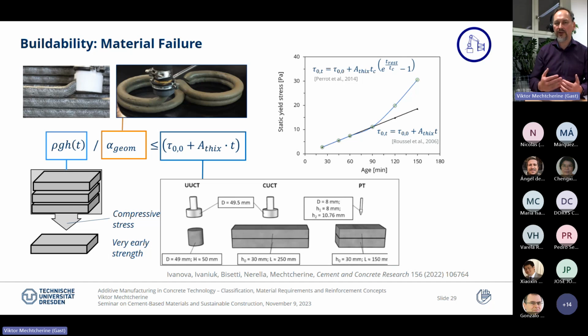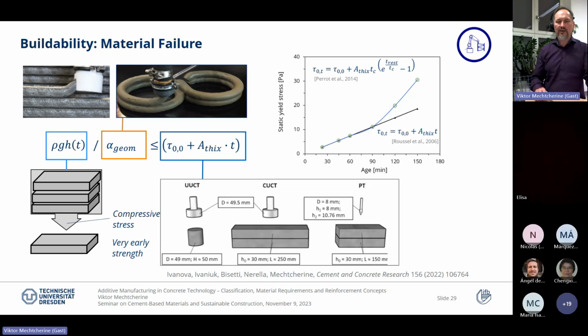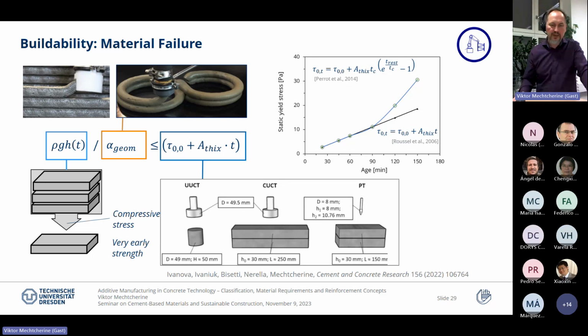What would be also development of this resistance in time, because putting layer after layer, we also have progress in time. So it means the time runs and the material we deposited first also develops in its properties. Again, I refer here to the previous presentation by Nicolas Roussel, who described also the phenomena occurring in the material. So basically, to describe this, we use approach like described here. So it's very similar to what I showed for one filament, but in this case, it's the height. It's not just height of one filament by height of the growing wall, right? And it, of course, also function of time as shown here.